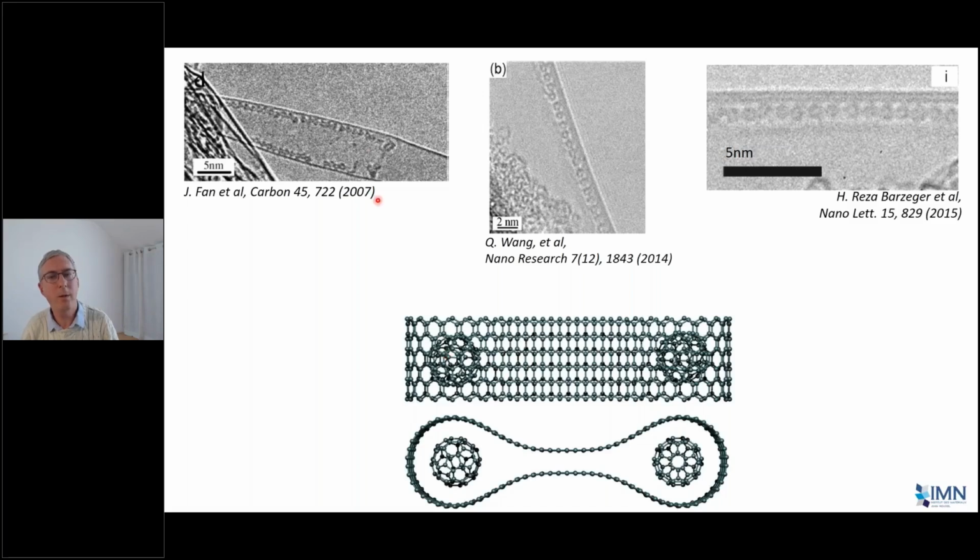So this is 3 examples where groups actually put C60, fullerene molecules, so football-shaped molecules, into the fold. And you can see from our calculations that the fold is now much bigger, because it can simply expand and contract to match the size of the intercalated molecule. So that's really nice. You can, in principle, use that in a way that you couldn't with a carbon nanotube, which would be fixed. So you can have a lot of fun playing with cavity size.